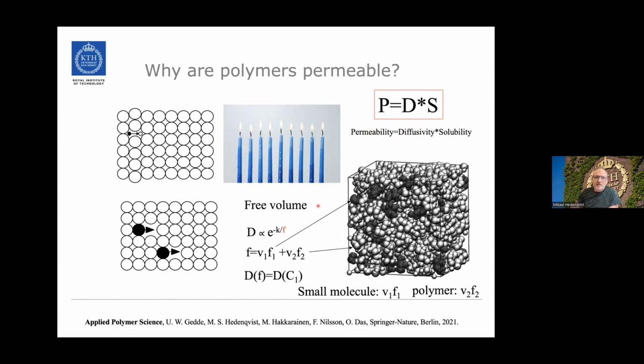And coming back to them, that they are not tight, they have a certain free volume. And that free volume is then open for foreign molecules to get into. And of course, the larger this foreign molecule is, the less space it will find for creating its own place. In the free volume theory, the diffusivity is exponentially related to the amount of free volume in the